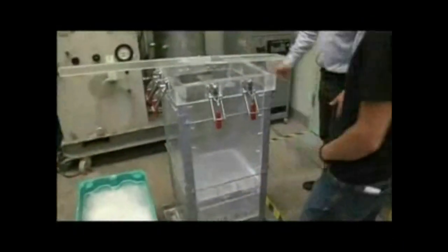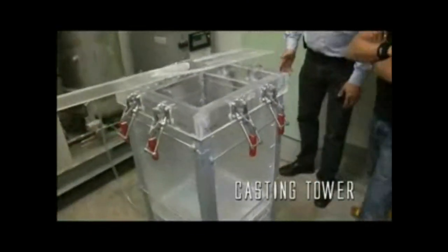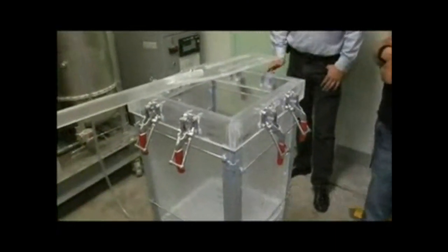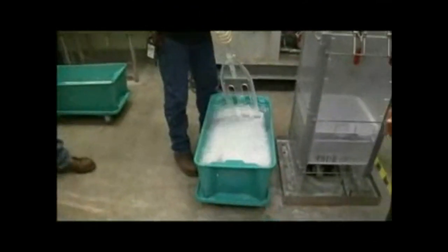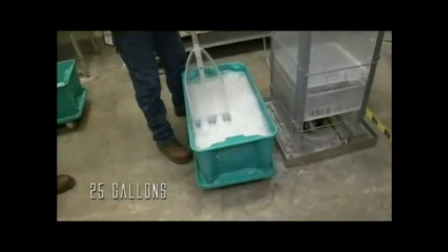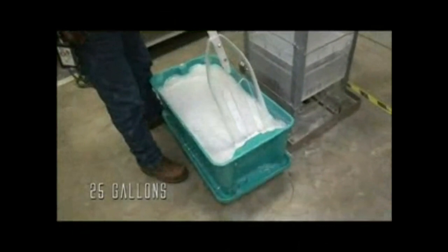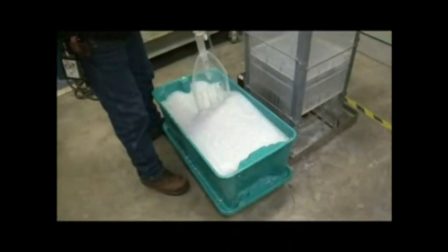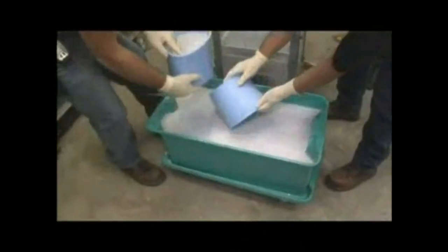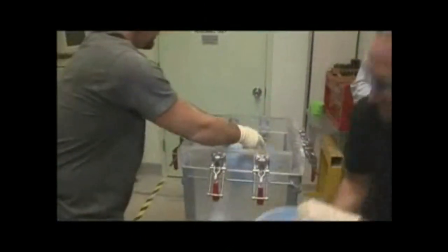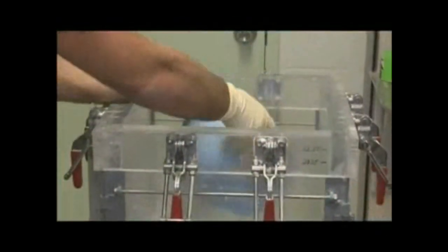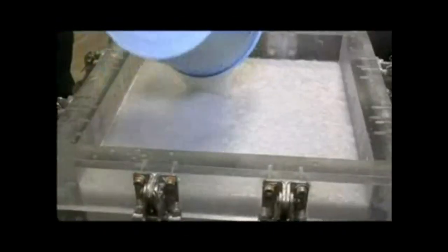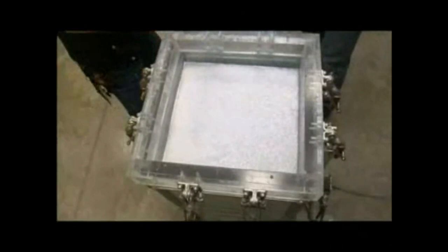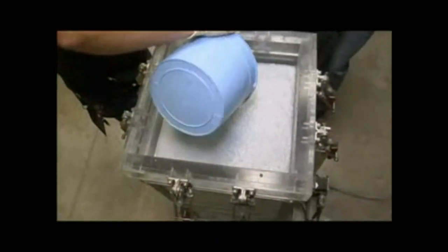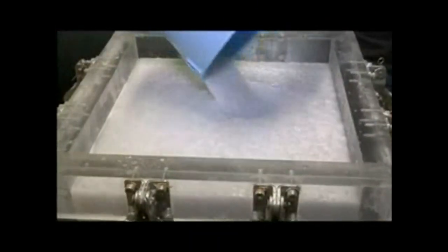This device here is called a casting tower, and it's really simply a hydraulic press. We have around about 25 gallons of the prepared slurry, which is the chopped fiber, water, surfactant, and the other additives. Sure. And we now go through the process of loading it into the press. And despite many years of high-tech methods of getting the slurry from the bucket to the tower, this is how we do it. It actually takes about 25 gallons of water to produce one block.